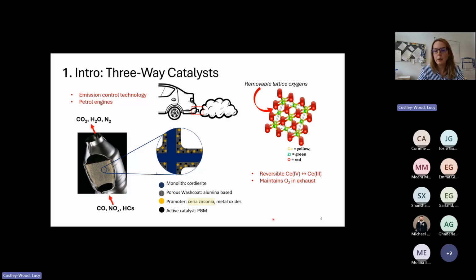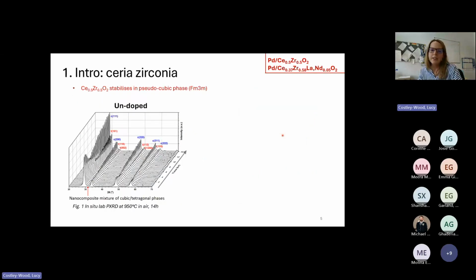It's also just a really good support material for the active catalyst, which is palladium in this case, but can also be rhodium or platinum. A major downside, however, to the ceria zirconia that I just talked about, the 50-50, is that it is not very thermally stable. It stabilizes in the structure I just showed on the previous slide. It's called a pseudo-cubic phase. It's more like, as labeled here, a nanocomposite mixture of cubic and tetragonal phases.